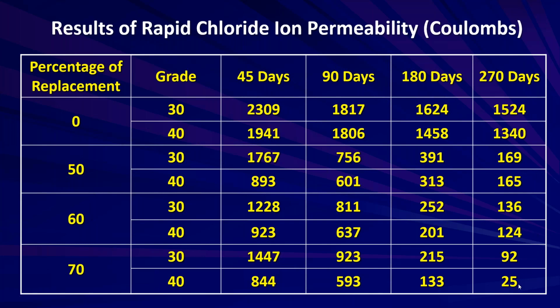As the time goes on increasing, the number of coulombs gets reduced. That means there will be pore refinement within the concrete. With 70% fly ash, at 270 days, the number of coulombs was only 25, and it gave very good strength also. By using the supplementary materials, I need not explain now at this stage.